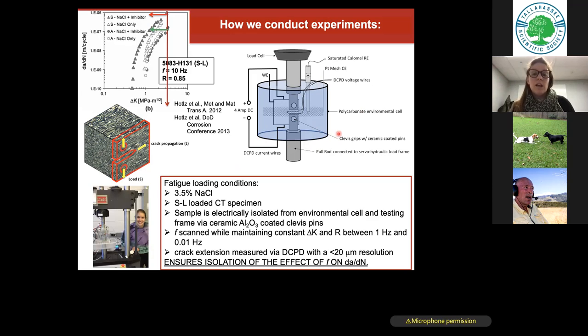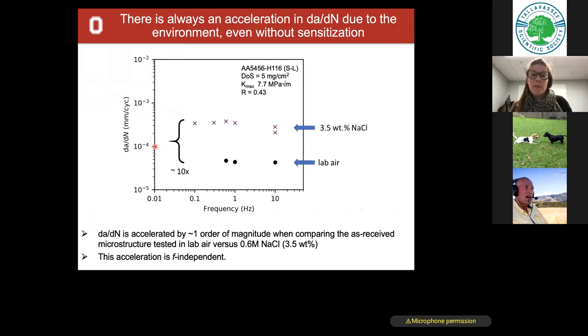And our goal here was to say, okay, if I want to change my loading frequency, I want to load it really fast, like they do typically in labs, or I want to load it really slowly, like I would for wave action, what happens and how is that different? And how does the effect of baking it in the sun alter what happens? So we can see some of that here. Here is how fast a crack will grow as we measure and how fast it's physically loaded.